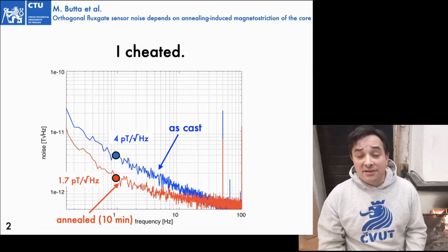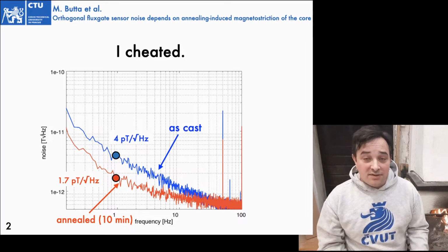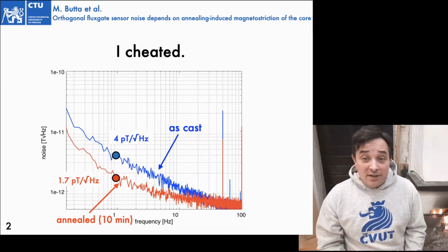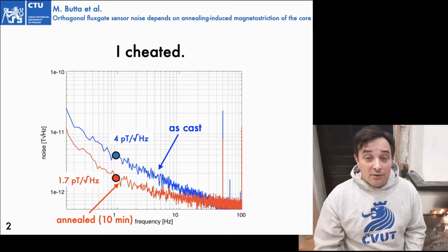For instance, here you can see the spectrum of the noise of a sensor based on a single wire, and you can see that if you anneal the wire, your noise gets about half of the original noise. And this is nice because you can just warm up the wire with the current for 10 minutes, and wow, the noise gets half of the original noise. And this is the part where I did not cheat.